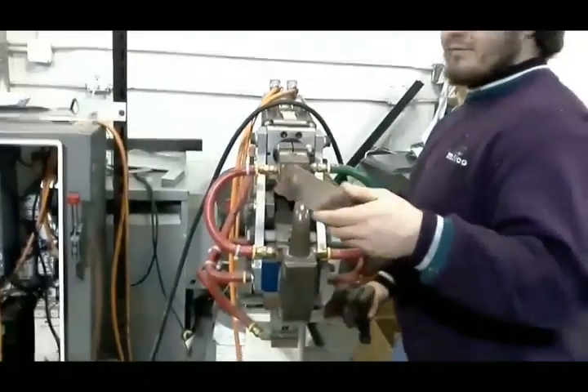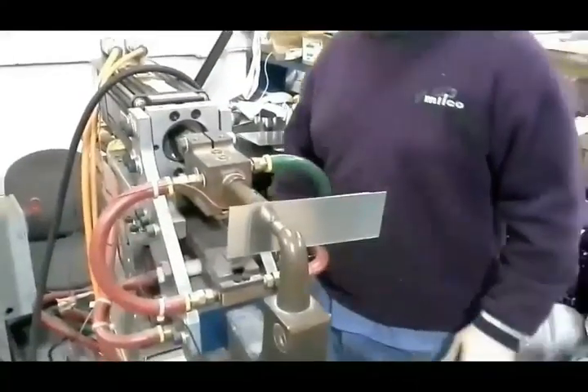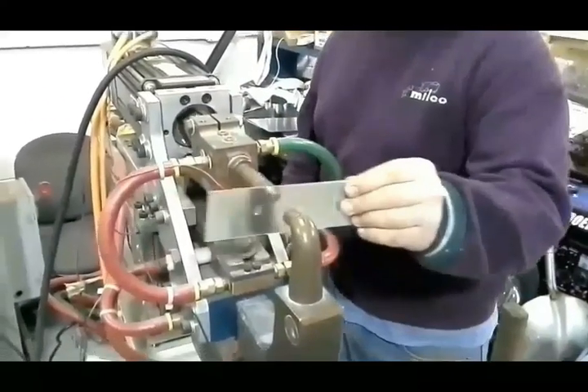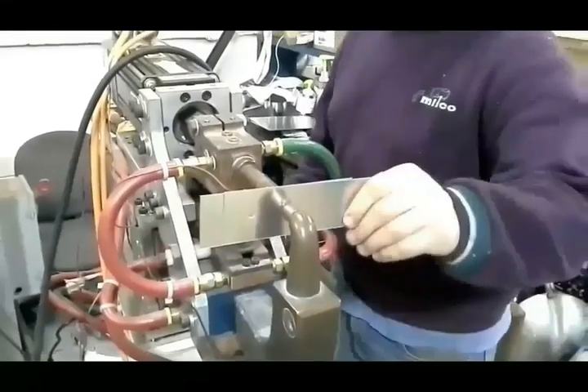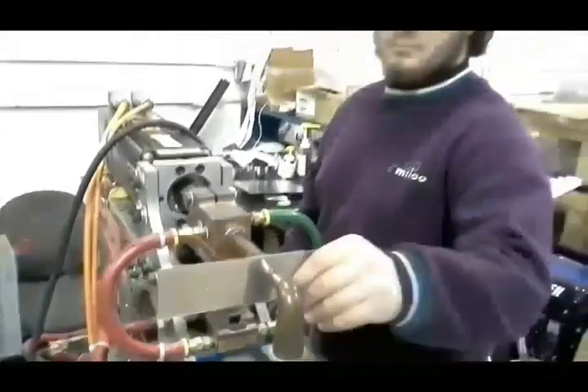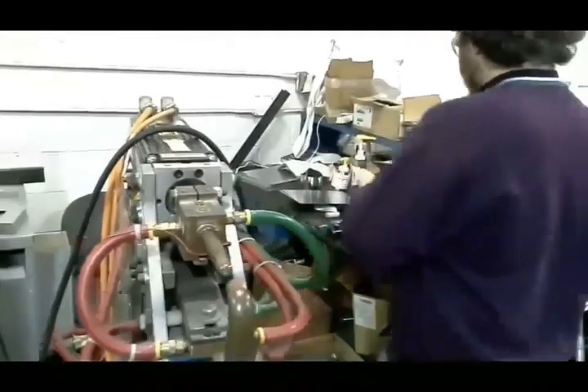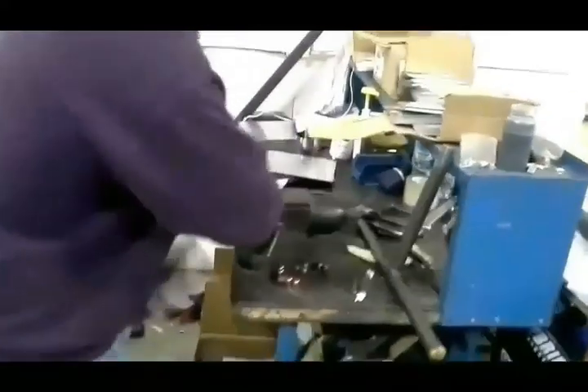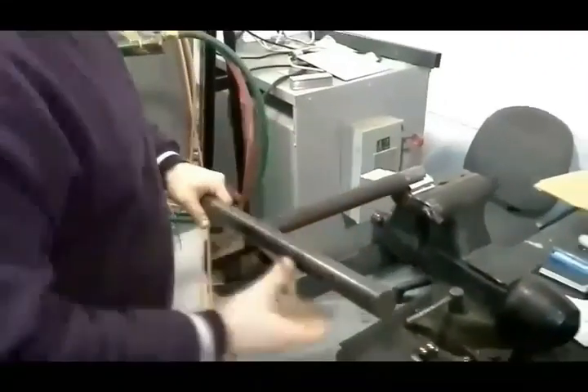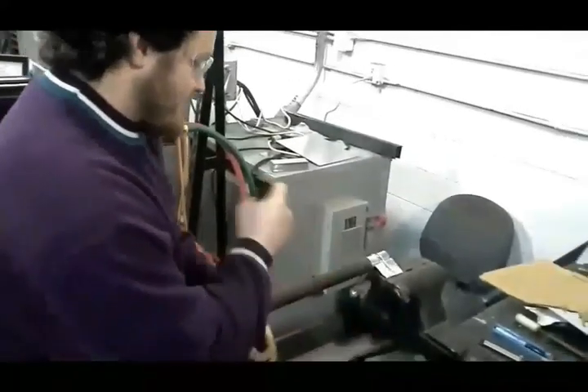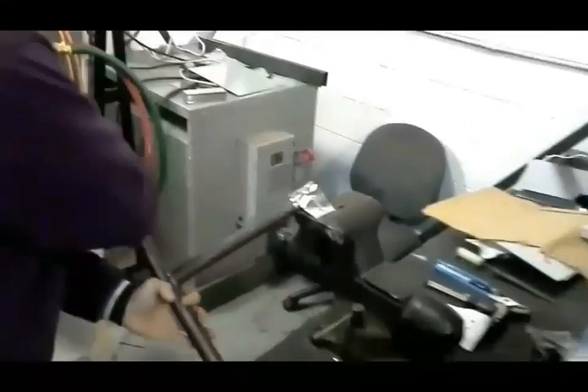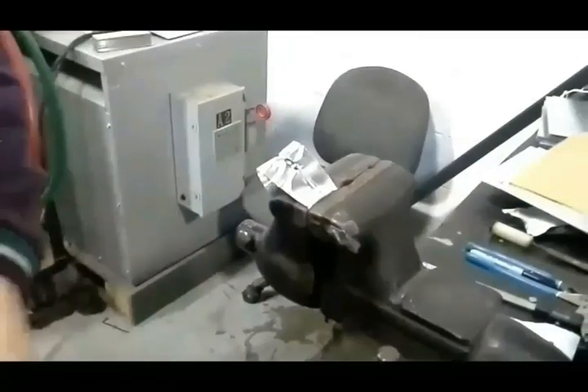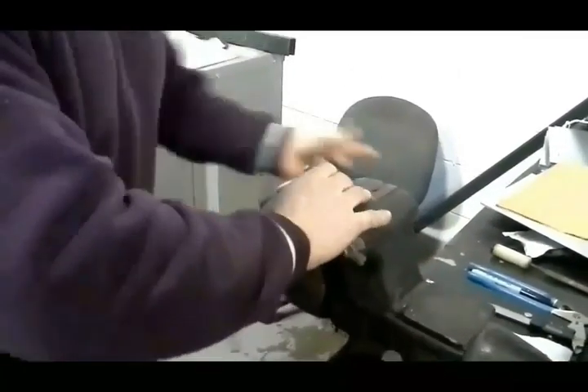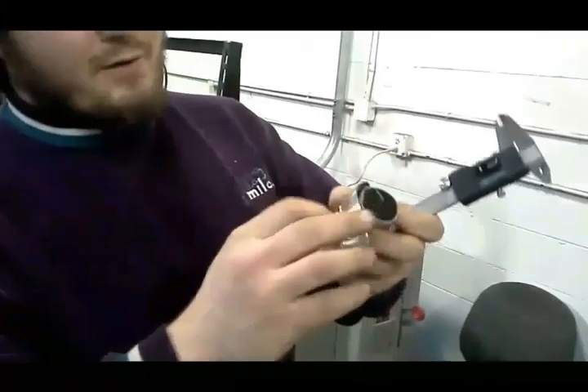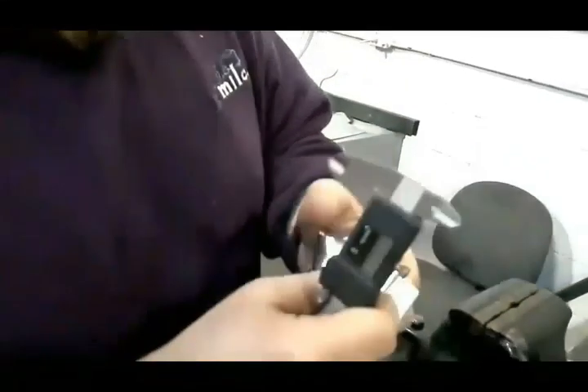If we have to do this coupon first. So how many points on the coupon? Three. Okay. Feel it. And you know it's a good weld when it's tearing away the base material with it, instead of splitting the actual weld.